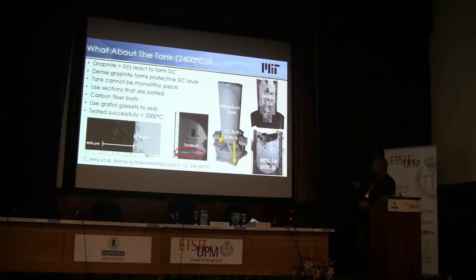And so one of the things we did was to try to prove to ourselves that this could work. So we use actual metallurgical grade silicon. It's only 98% pure. We built a little miniature tank, so this is only about 6 inches tall. It's got two pieces, a top half and a bottom half. So right here at this seam is where the seal is. If you did nothing, if you put nothing there, this is exactly where the liquid will want to leak out, because it's two pieces that are pressed up against each other.